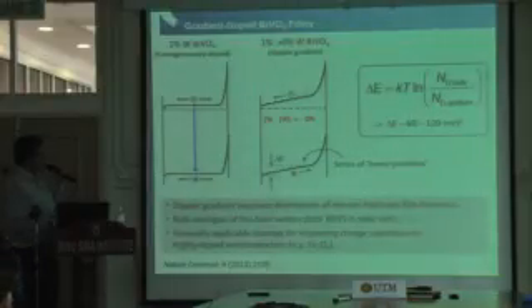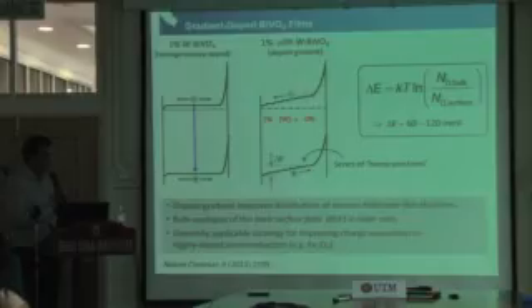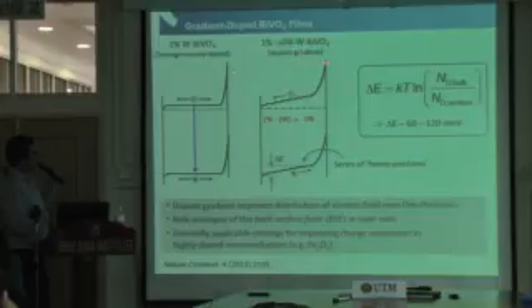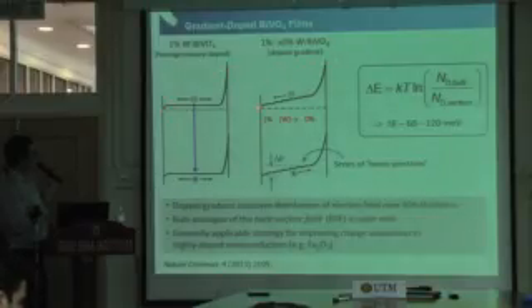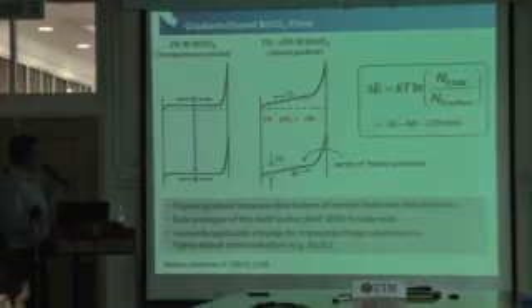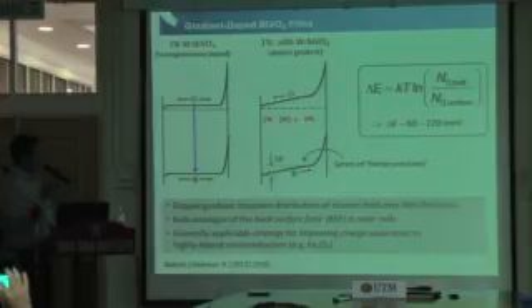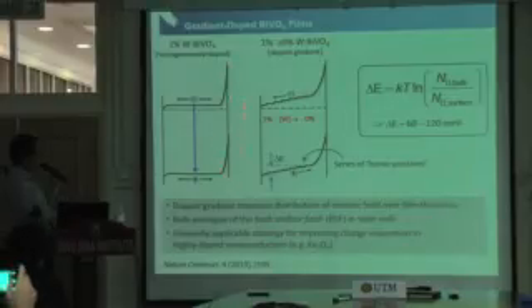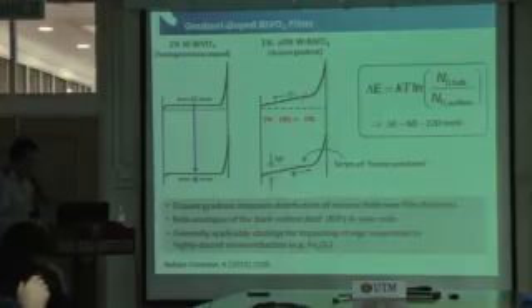And if we go a little bit into detail into how it actually looks, in a homogeneously doped and in a gradient doped bismuth vanadate, the total potential drop from the interface here at the back is actually the same. So comparing this and that is actually the same. But what we effectively did is that we distributed the electric field over the entire film thickness. Whereas here it actually only happens at the surface, here we distribute it over the entire film thickness. So this is a bulk analog of a back surface field in solar cells, and we think that this is generally applicable for other highly doped semiconductors as well.